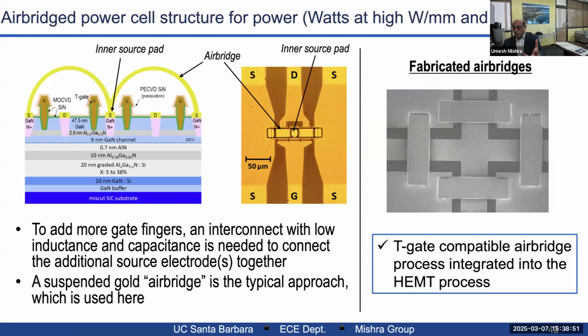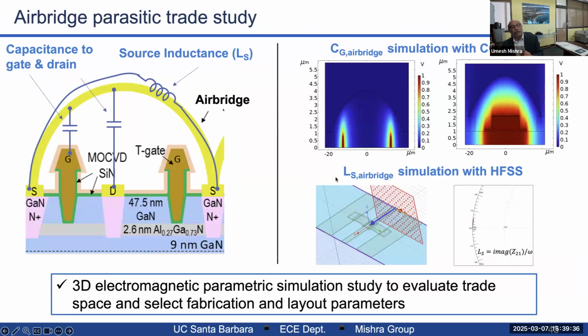Watts per millimeter is nice, but what you need is watts. So for that, you have to have an air bridge structure like this. Axel and Henry Collins worked together on this. What we did was air bridges over multiple fingers, like every self-respecting MMIC designer does. But the only difference was that we also used the air bridges to do impedance matching close to the device. So this is a pre-matched device, not fully matched, so that the load pull system could match the device better. We did a lot of modeling, both by COMSOL to get the capacitances right, and by HFSS to get the inductances right. We did all this because you have to do it right to create the right matching circuit.